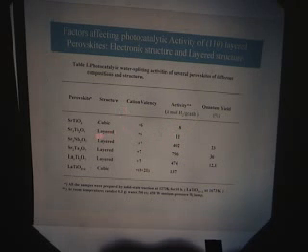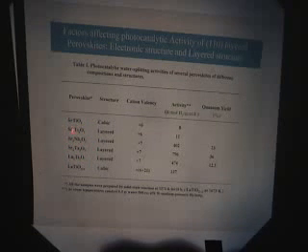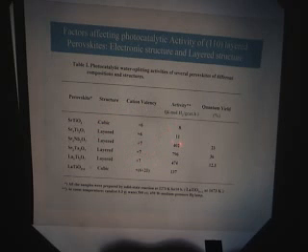And then, if you replace this titanium with the pentavalent niobium or tantalum, or replace this strontium with the trivalent lanthanum, you have the 110 layer perovskite, all having the cation valence of +7. And this material showed greatly improved photocatalytic activity. So it seems this special, particular electronic structure is the most important factor.